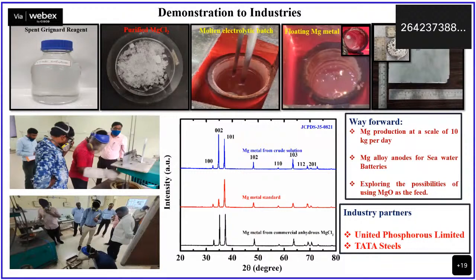So the way forward is, we are also working with high energy batteries for the production of magnesium alloy anodes for seawater batteries. The idea is to scale the process up to 10 kg per day with the data available from the extraction of magnesium from both primary and secondary sources. Right now we rely on United Phosphorus Limited and Tata Steel for the funding.